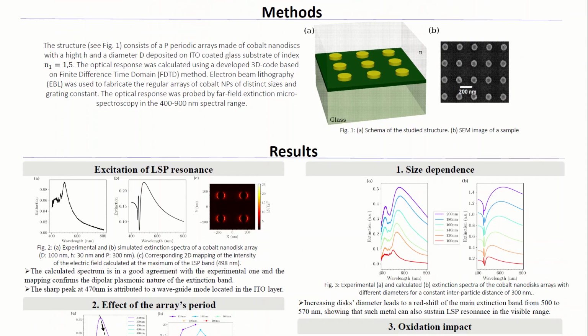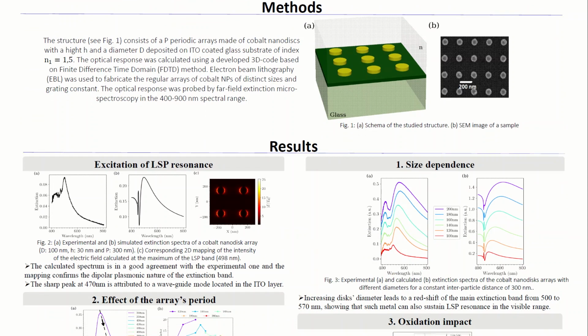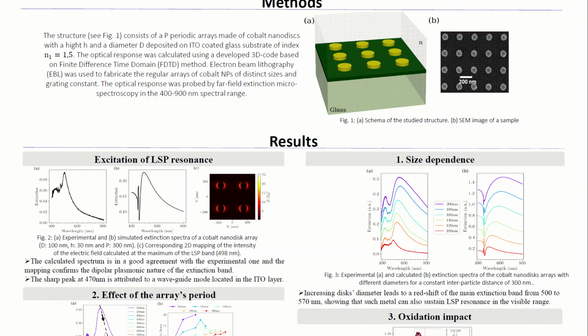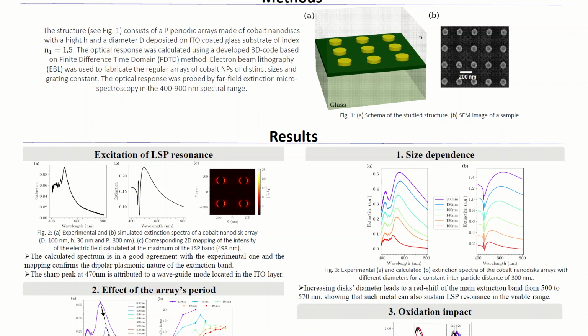Let's first evaluate the capability of cobalt to sustain localized surface plasmon resonance, LSPR, by considering an array with typical dimensions sustaining an LSP mode. Both calculated and measured spectra agree to display a strong extinction, indicating the excitation of LSPR, confirmed by the mapping of electric field intensity showing a mode of dipolar nature. We also observe a sharp peak at 470 nanometers attributed to a waveguide mode in the ITO layer.